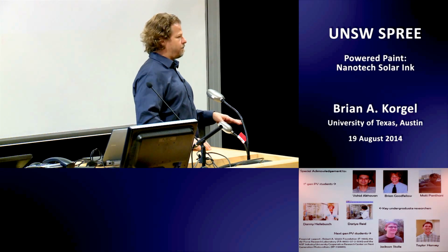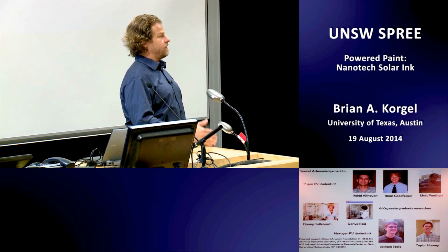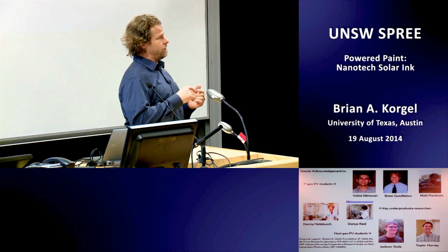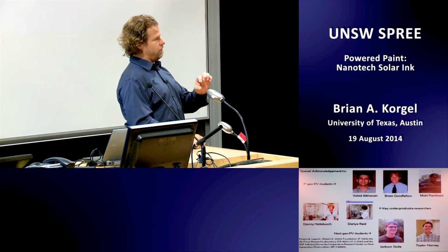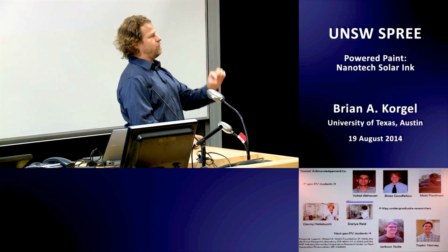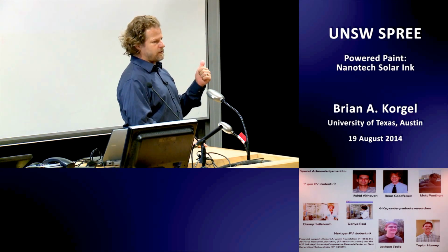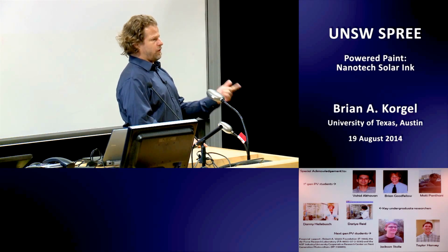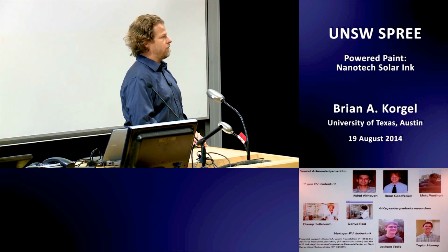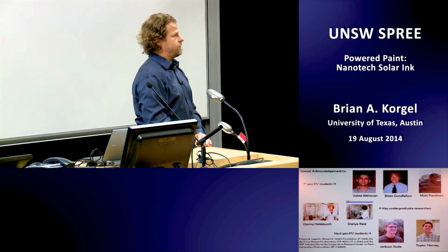And actually, by doing that, by either adding a thiol versus a bromide-containing surfactant, both the Sargent group and Bawendi's group have measured substantial shifts in electron affinity of these layers. They'll actually build heterojunctions of lead sulfide nanocrystals with two different types of capping ligands just by doing that. So the capping ligands play a role of passivating interfacial traps, for sure, but they can also shift the energy levels of the nanocrystals. And when you're making a device, energy level matching between the different layers is really important.